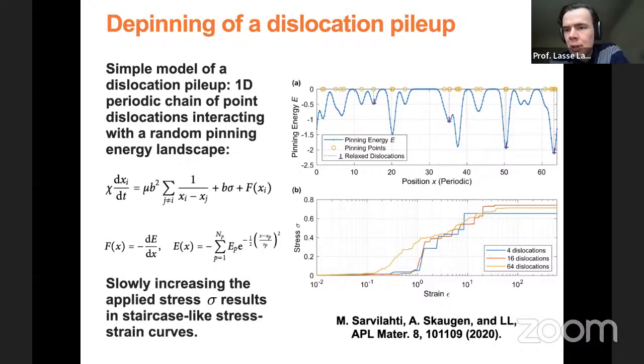It doesn't really happen in the 2D system, because there you will get some structure formation. So the dynamics is not stationary, in the sense that you will form more and more complex structure as you accumulate more and more strain. So you don't really have that. But in this case, where you have this simple 1D model with quench disorder, there you have this onset of flow. So is it possible to predict the point where it starts flowing?